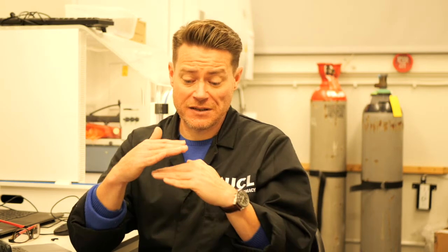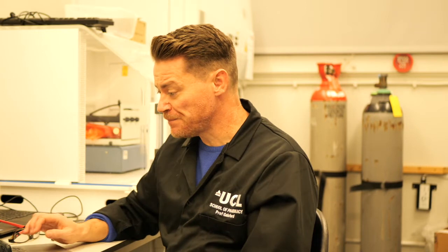It's also possible to control the temperature and the humidity that your sample is sitting in, and the reason is because the actual AFM itself is quite small. It's just a motor moving this tip plus your sample. So you can put all of that into a box, and when you can get things into a box, you can temperature control that box and you can control the humidity. So you can do things like increase the humidity and see what happens to the sample, or increase the temperature and see what happens to the sample. It's quite a useful technique.